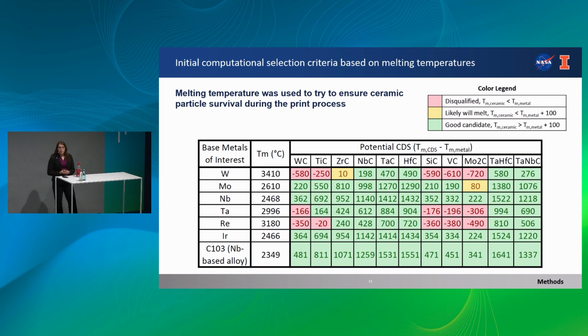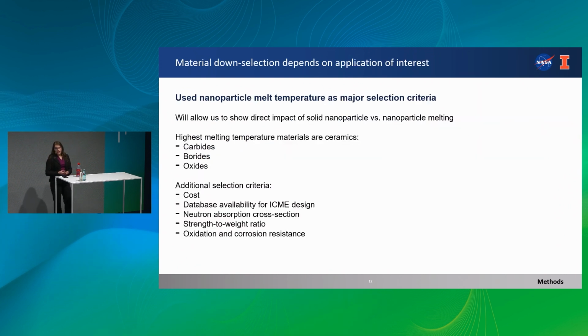So as you can see, if you compare the melting temperature of carbides to a lot of these refractory materials, that actually doesn't really narrow down much. But additional selection criteria that you can account for are things such as cost, database availability, your integrated computational materials engineering designs, as well as, in our case, neutron absorption cross-section. You can include things like oxidation, corrosion resistance, strength-to-weight ratio, et cetera, and how much these things can affect your properties. So really it depends on your application of interest, but you can use this to really narrow the playing field down. So we mainly have focused thus far on tungsten and molybdenum, and on zirconium carbide and tantalum carbide, since those are the two carbides that have higher melting temperatures than tungsten.